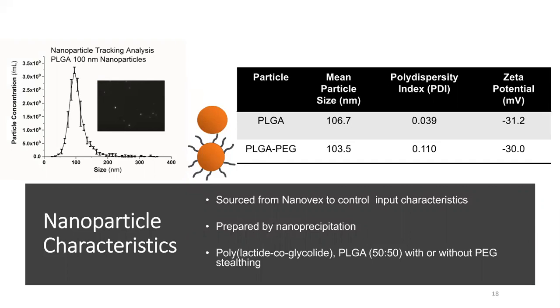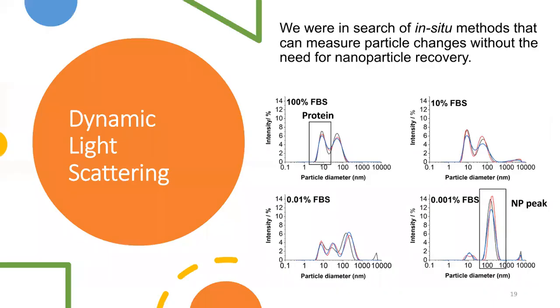And this is known to have an impact on the specific composition of the protein corona that will develop, but we haven't got quite as far as this yet. So at first, we're looking for an in situ method that allows us to measure the change in particle size without needing to recover the nanoparticles first. So we've analysed by dynamic light scattering solutions of nanoparticles in various concentrations of fetal bovine serum.